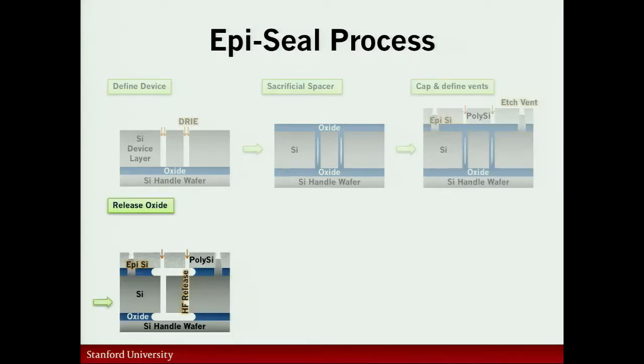We use an HF vapor etch to go down through the small holes in the poly and etch out the oxide that surrounds the micromechanical element. The nice thing about the HF vapor is it tends not to leave any condensation behind, so we don't have problems with capillary forces and stiction. And it's otherwise pretty clean. It leaves behind a hydrogen-terminated silicon surface, which is pretty cool.